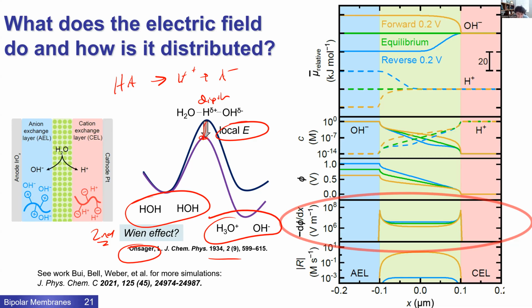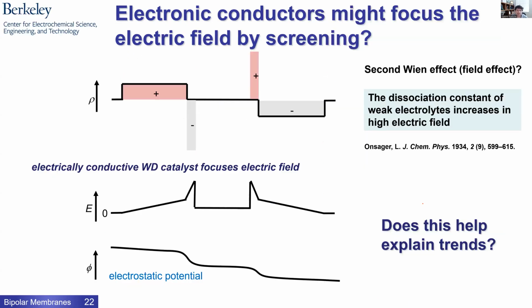I can lower the transition state free energy through that dipole field interaction, and that will speed up the rate. The activation barrier for the process goes down. And of course, I just told you we have fairly strong electric fields in these junctions. So maybe there's something to be said here for how the electronic properties of this catalytic material affects this.